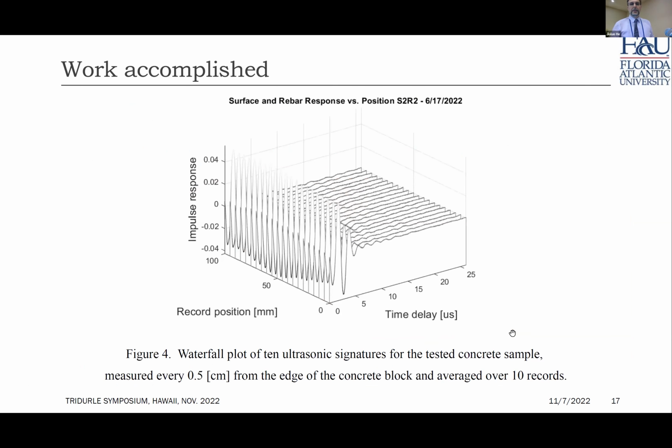bottom rebar. So the way we actually perform our operation, we do all our data acquisition, we collect our raw data. Again, this is a low budget project, so this is not very sophisticated, but we use what we have and it works. So here you see a series of data collection after time averaging of this very high frequency signal. The strong signal is the echo coming from the surface of the concrete, and this very faint echo over here is that of the rebar.